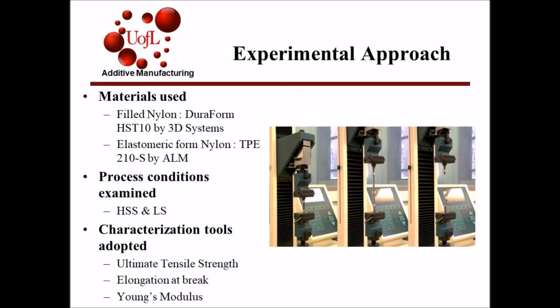The two materials used were a filled nylon called Duraform HS T10 by 3D Systems and an elastomeric form of nylon called TPE 210S by ALM. Optimal process conditions for the laser sintering and high-speed sintering process were chosen such that the mechanical properties will be maximized. For the laser sintering process, previous studies were used to determine the laser power settings that would maximize the mechanical strength properties. For the high-speed sintering process, the build bed temp and the infrared lamp power were also optimized for maximum mechanical properties as well.